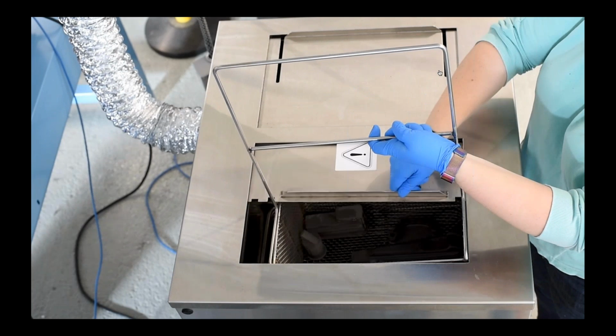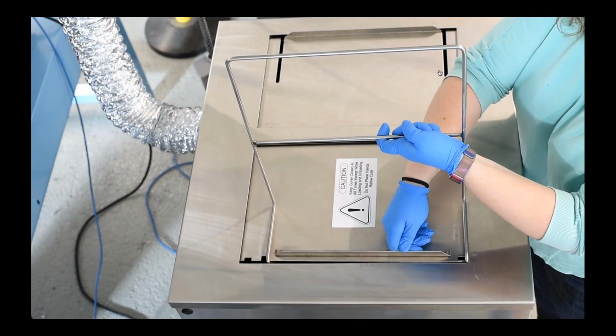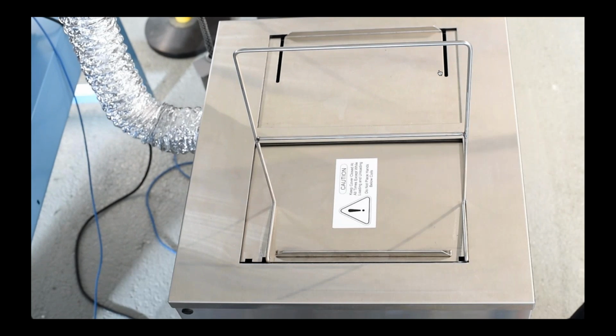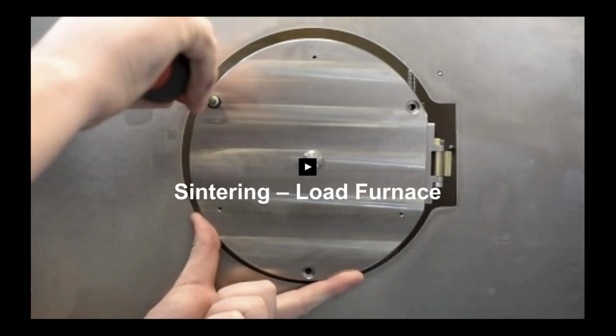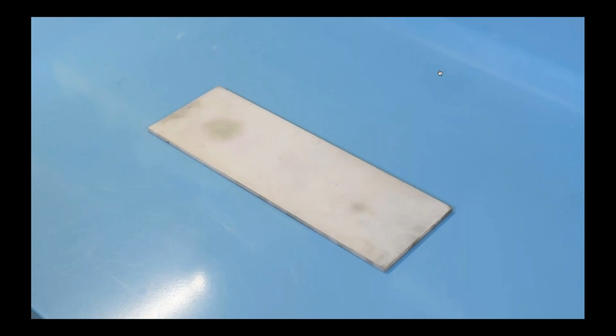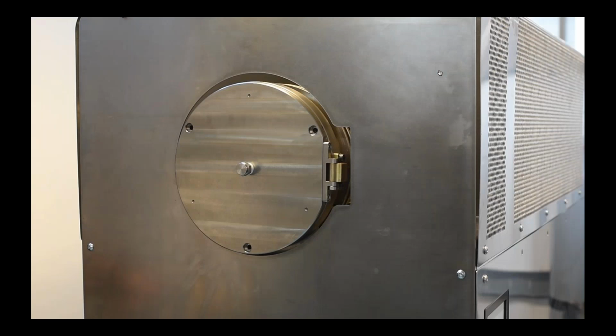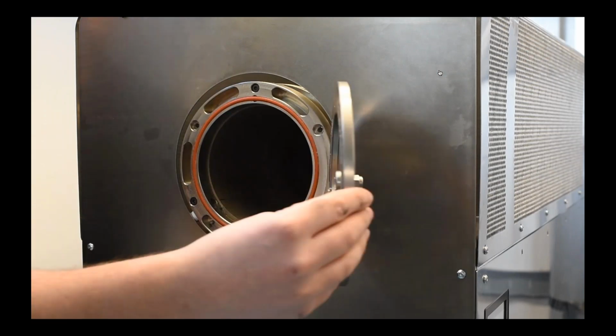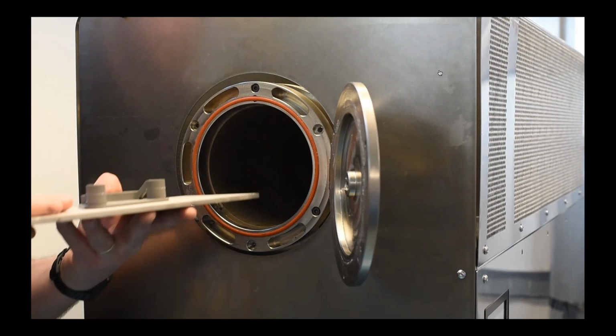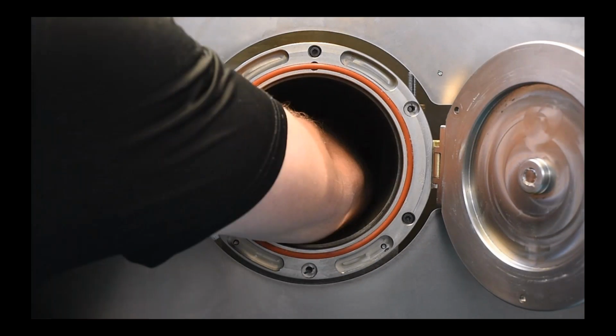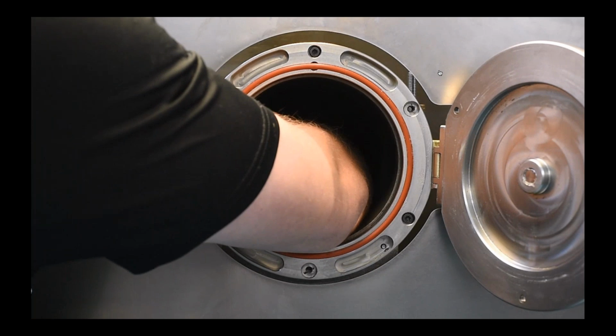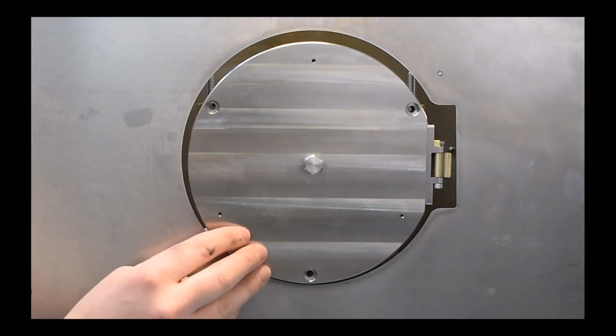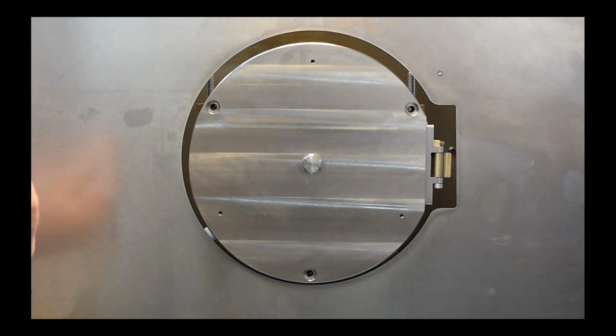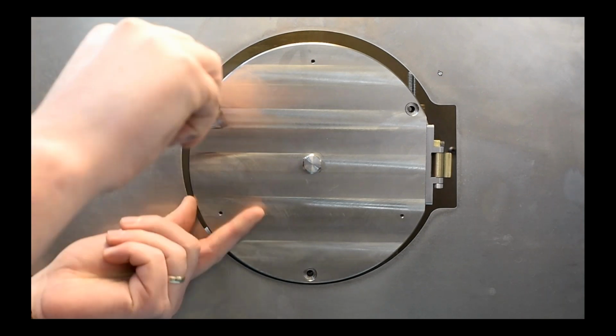From there, remember you weighed the part before you placed it in there. You now reweigh your part. As long as it dropped 4.2% by mass, your part is ready to go into the sinter oven. This is a video of how they're loading a part into the sintering oven. That part is now a brown state part. It's done washing. You place it on the setter plate, and you slide that setter plate into the sinter oven. Right now everything's at ambient. You seal off the sintering furnace, and you kick it off. So he's sealing it off now.